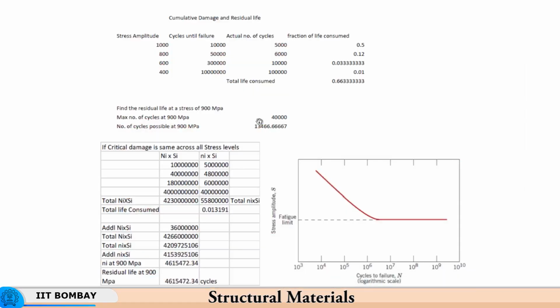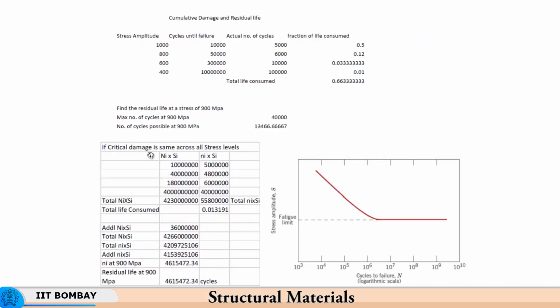So, what it means is I can get it without any kind of breakage or any kind of failure. So, I get 13,466 cycles at 900 MPa. Now, if you look at the critical damage being the same across all stress levels, then I get a completely different picture.